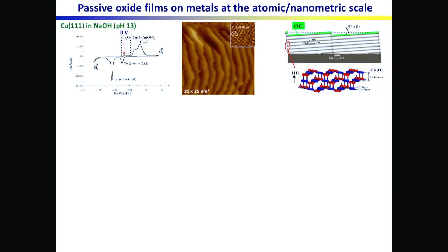So first I would like to show you the link between electrochemical measurements on pure metals and formation of the oxide film and the detailed structure of the oxide. So here this is the case of a copper single crystal, copper 111 in alkaline solution, and I'm sure many of you are familiar with the voltammogram, where you would observe, after a range which I'm not showing today but we have studied in many details, where you have only adsorption and desorption of OH groups, but then you arrive in a range where you form Cu+ and Cu2+ oxide, and these oxides can be reduced with two clear waves in the reduction.